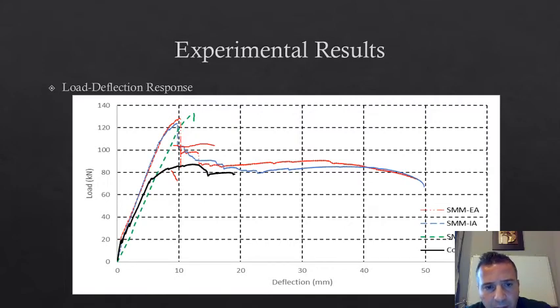The anchored beams have slightly lower failure load than the unanchored ones, but they failed at a larger ductility. You can see they exhibit more deflection till failure than the control unanchored specimen. This means that the failure will be ductile, and they failed by yielding of the tension reinforcement and concrete crushing, so basically similar to conventional concrete. The unanchored specimen failed by debonding of the sheets from the concrete surface.